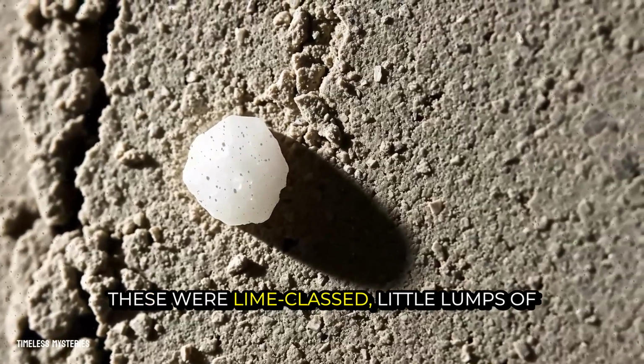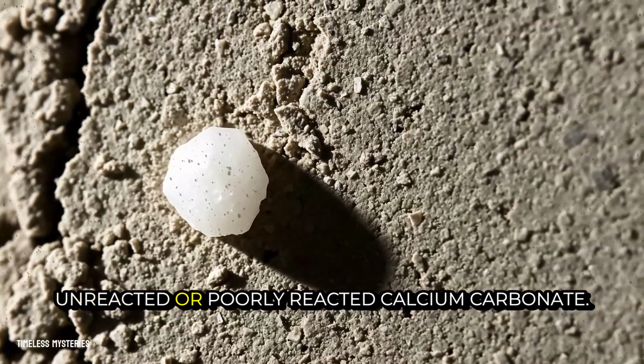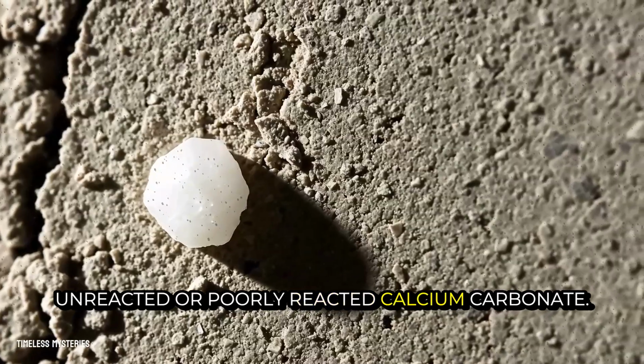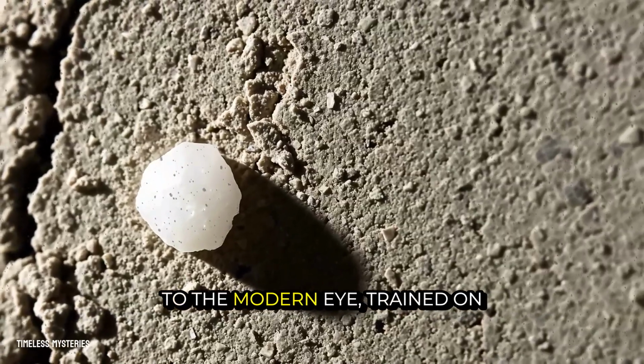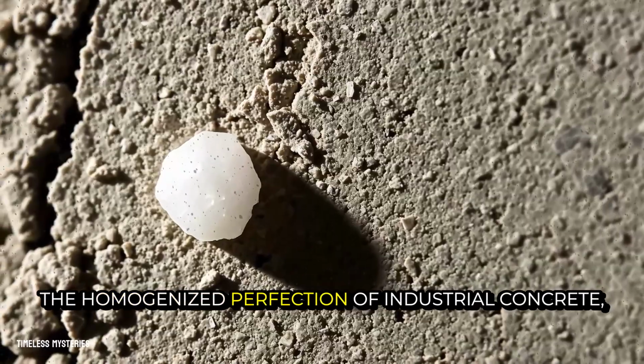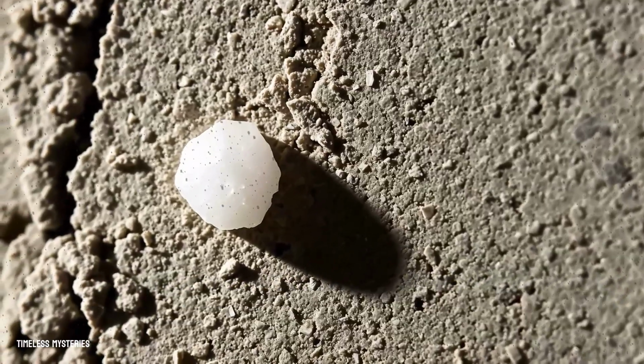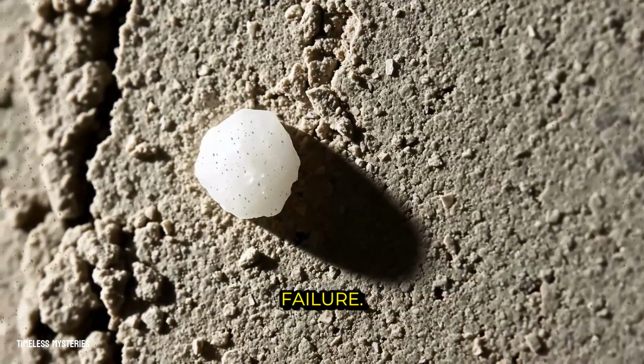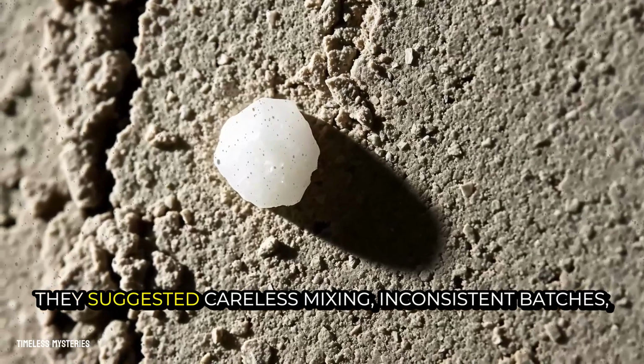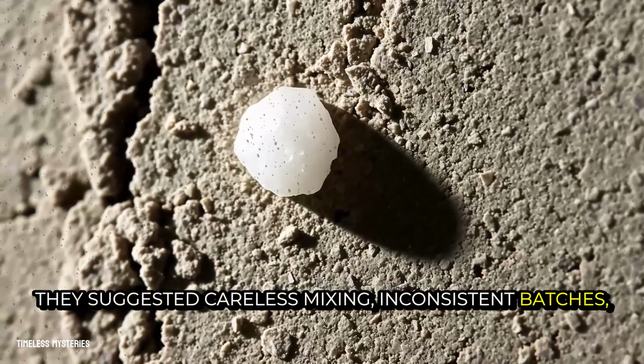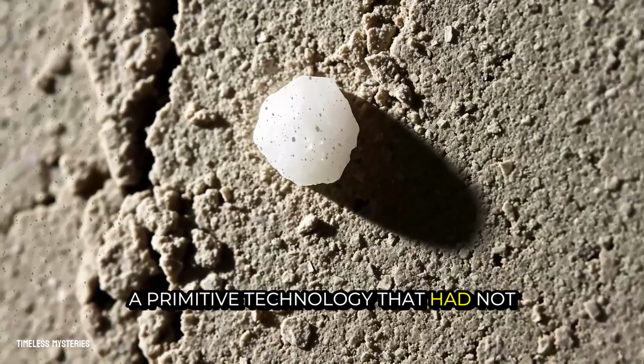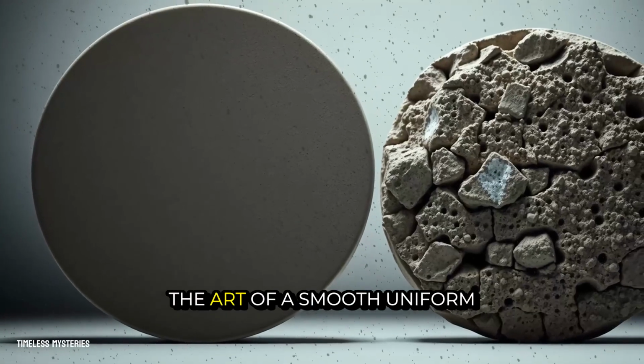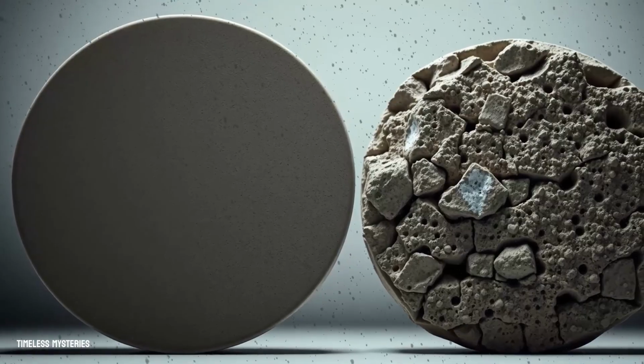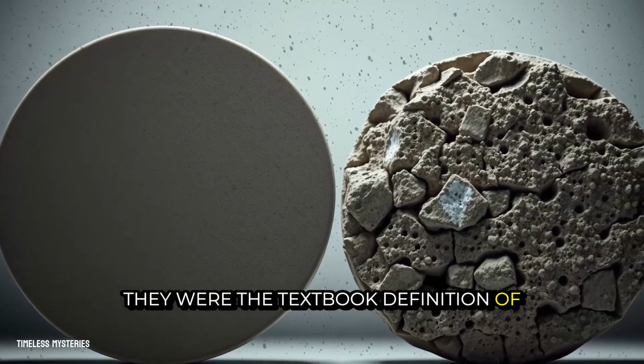These were lime clasts, little lumps of unreacted or poorly reacted calcium carbonate. To the modern eye, trained on the homogenized perfection of industrial concrete, these inclusions were a sign of failure. They suggested careless mixing, inconsistent batches, a primitive technology that had not yet mastered the art of a smooth, uniform blend. They were the textbook definition of a defect.